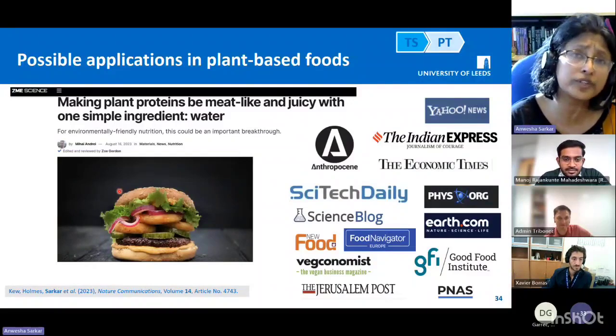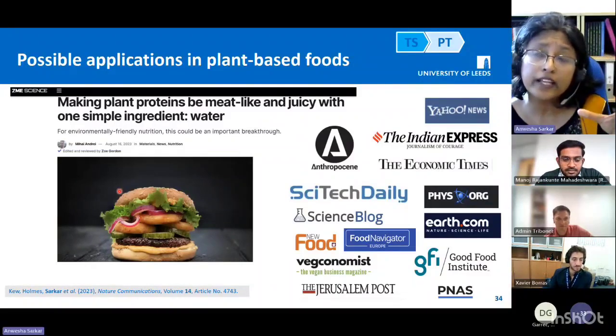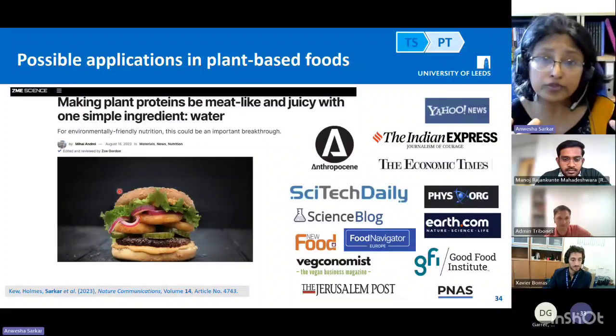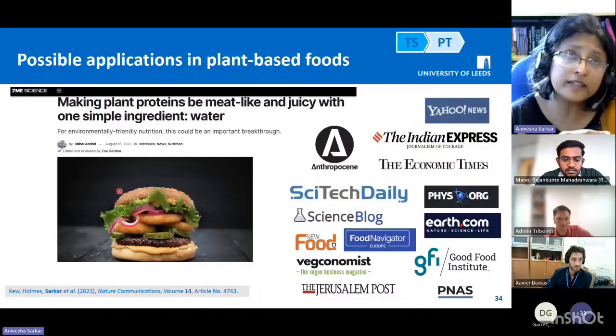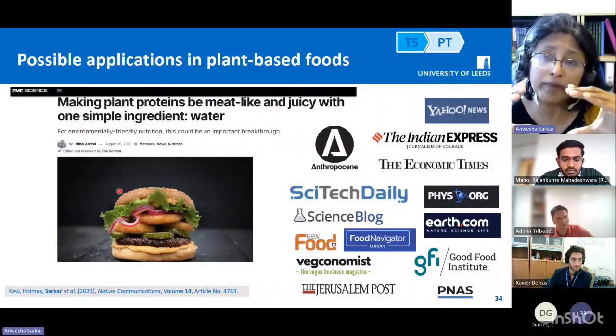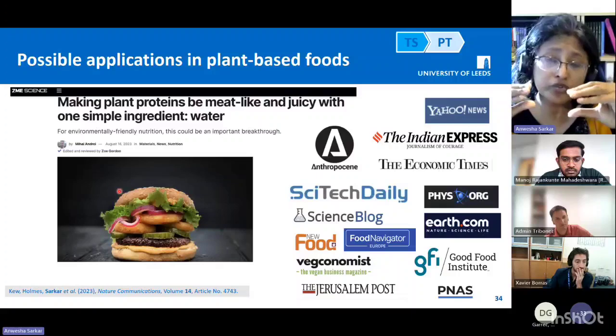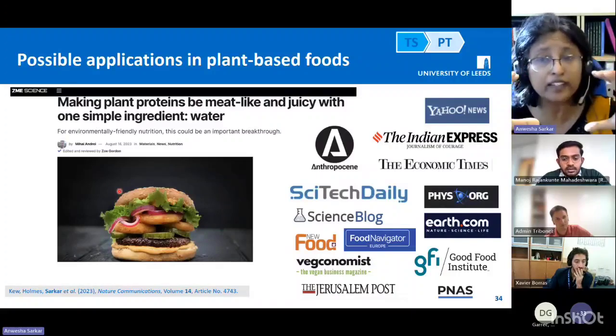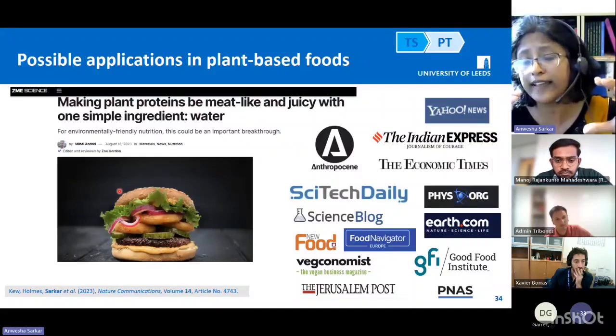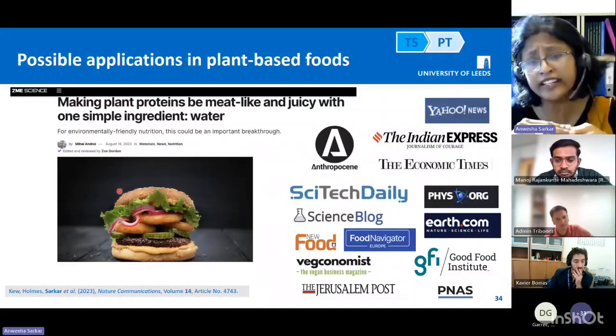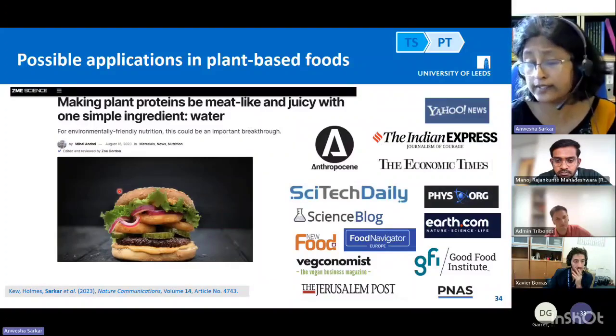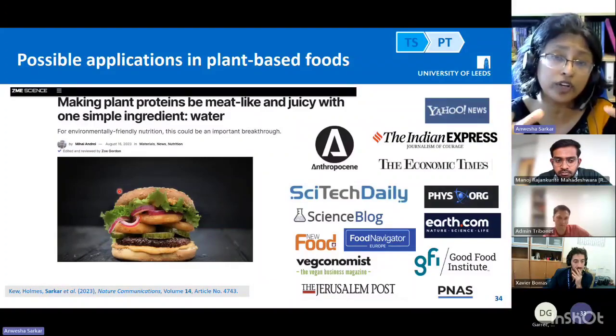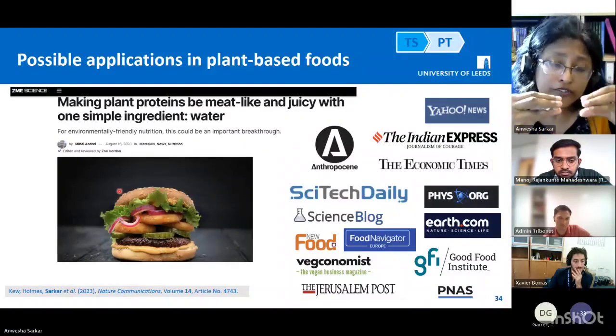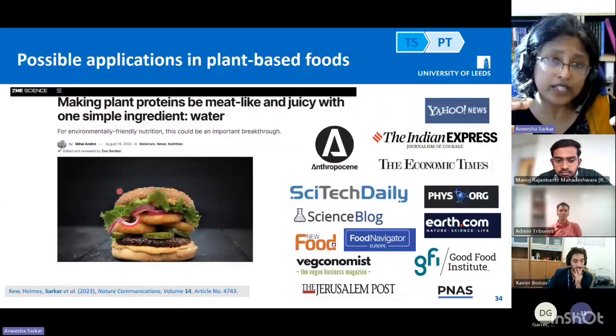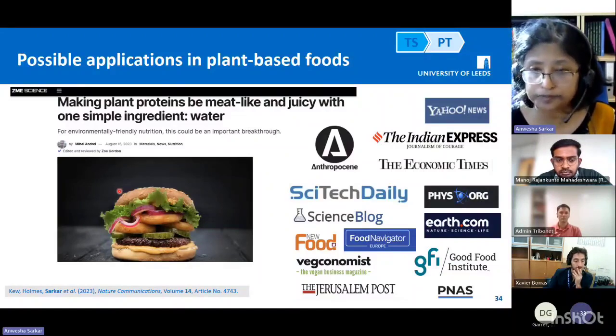But I think there are two stories to it. One is it goes to the protein and makes it hydrophilic. But most importantly, we did some load experiments, and we identified that these microgels were actually soft material which were squishable, but they were not destroyed. So they were keeping the viscosity constant, which is very exciting. And that's one of the reasons why you were getting such low friction behavior, which was pretty exciting. So you are creating a material which releases some amount of water, creates a hydrated layer, but is not destroyed by shear. So that's the beauty of creating microgels.